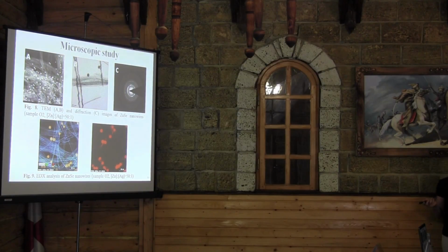But you don't have selenide signals there, so you don't know if there is a selenide. No. The spots are very clear in red. That means it's silver. I also did this on thin film, and it's difficult to incorporate silver in thin films. It's very complex because I always get nanocrystals of silver separately. So the word doping is different from monodispersed.